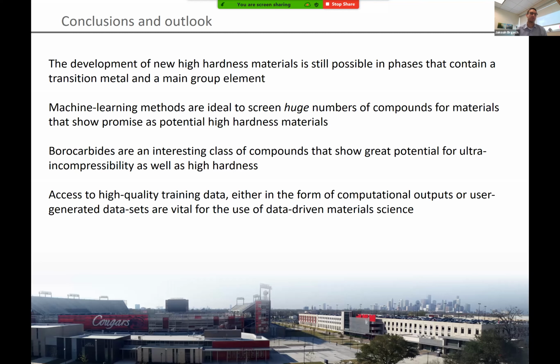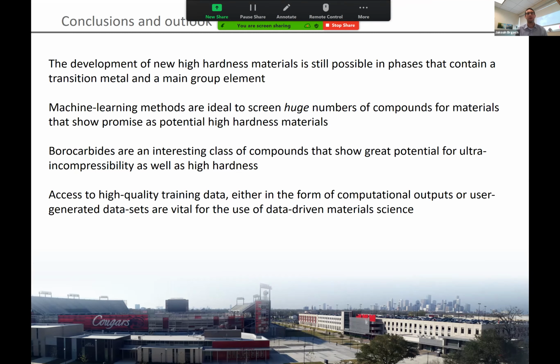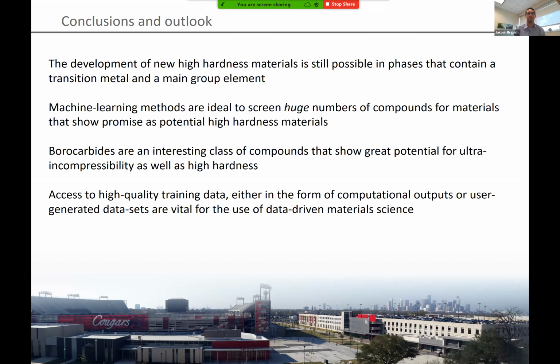Yeah, that's a cool question, because we actually just put out a paper that was accepted today in JPhysChem Lett, so keep an eye out for that. It's looking at how temperature affects hardness, and temperature is detrimental to hardness. Something like diamond, you actually have other issues with, and that's the fact it starts to sublime above about 500 Celsius. So if you put it in an atmosphere, the hardness of diamond drops by something like 50% at about 1,000 Celsius.